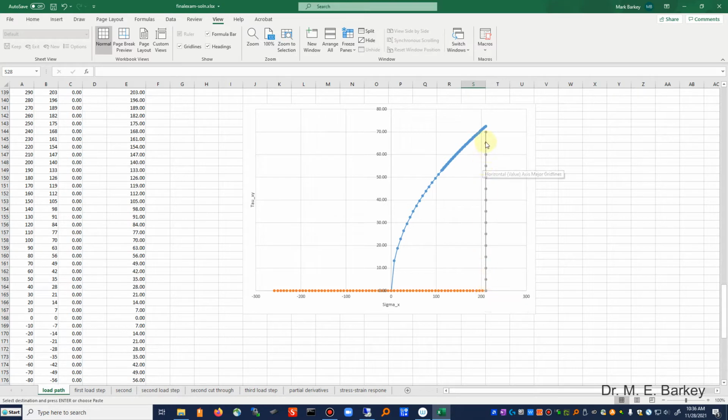And so what I'm going to do is set up my spreadsheet where I don't have any d alpha calculation. The alpha stays constant, but I am going to increment the elastic strain state based on the stress increment. The plastic strain state will stay the same. So my final total strain state minus the elastic strain increment as I move down through here will get me to the strain state that corresponds to this location.